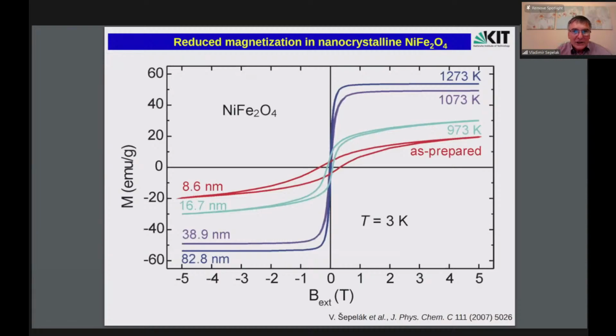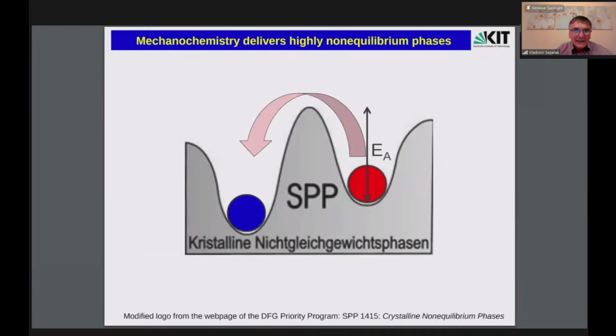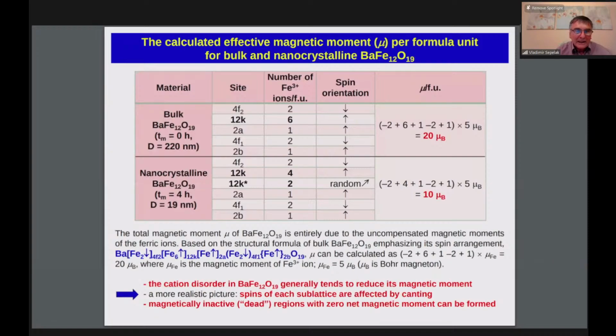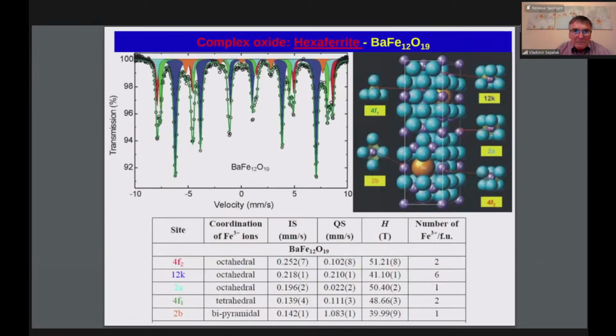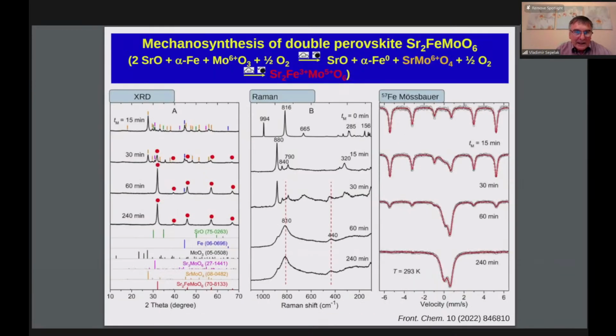The reaction time of mechanochemical synthesis varies depending probably on the conditions of milling and on the material. You see here, for example, double perovskite at 240 minutes, and we stopped here because we do not see traces of adducts. In this case, here is the Mössbauer spectrum, that means hematite. But sometimes, as I showed you, more than 10 hours of milling is needed.